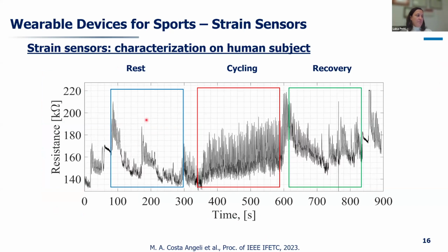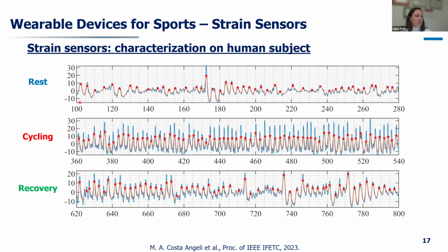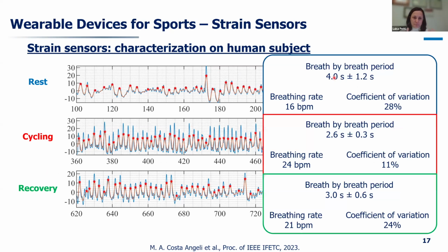This is the resistance change over time for the various phases, so the rest, the cycling, the recovery, and from those patterns, we can clearly see that there is a variation of the parameters. So in terms of breathing rate, what you can see, from the resting to the cycling and then the recovery, in terms of breath by breath period. So these are all patterns that were able to be distinguished.